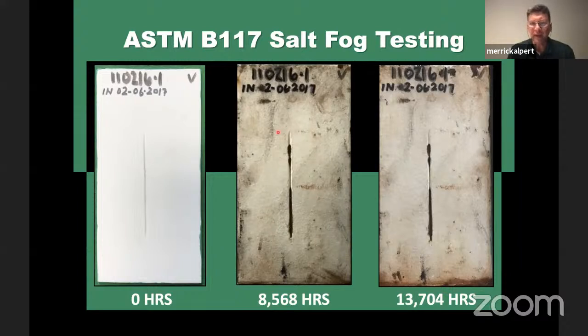And why is that? Think back to the scanning electron microscope picture you saw. Because you've passivated the steel, you cannot get behind that passivation layer. You can't get behind the alloy layer. And so the long and short of it is, yes, you can mechanically damage it, but it will never grow. You will not see a growth in the area that you've damaged.